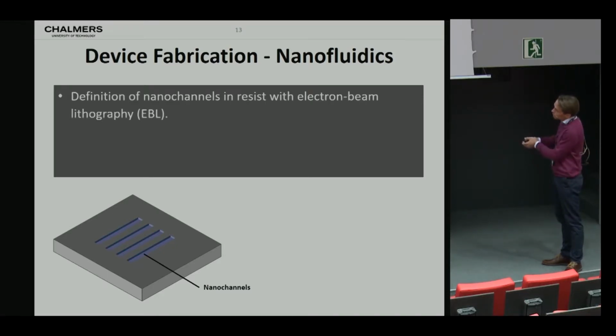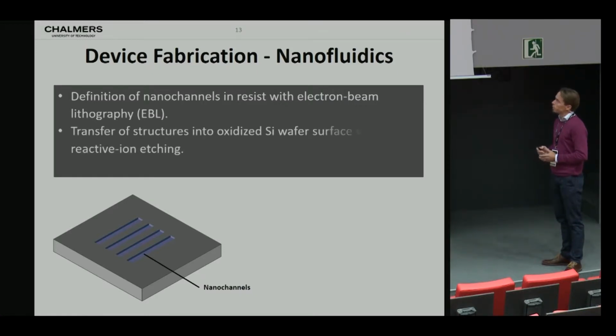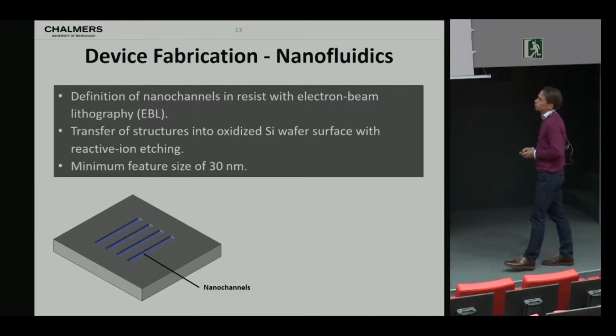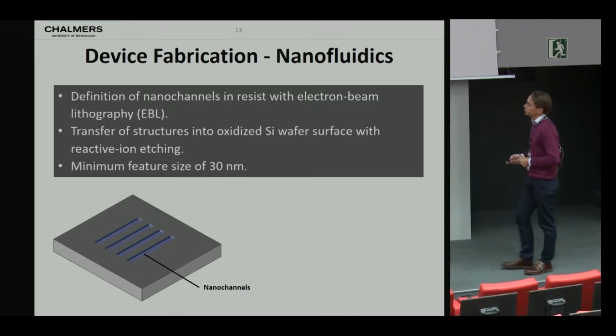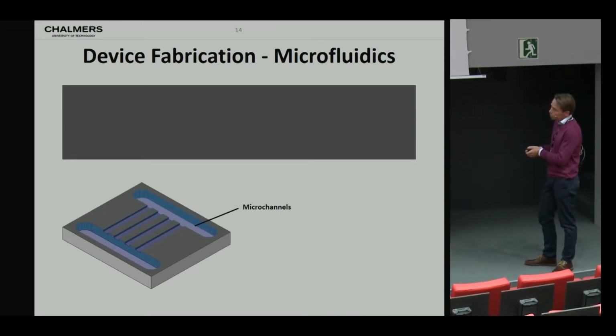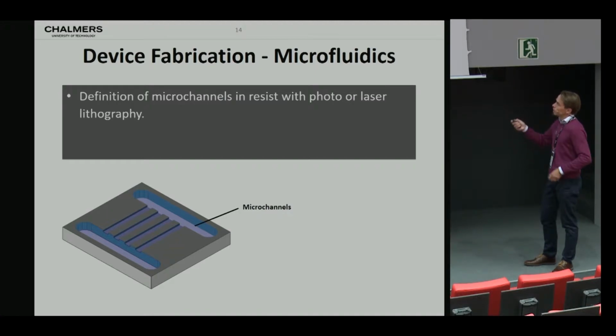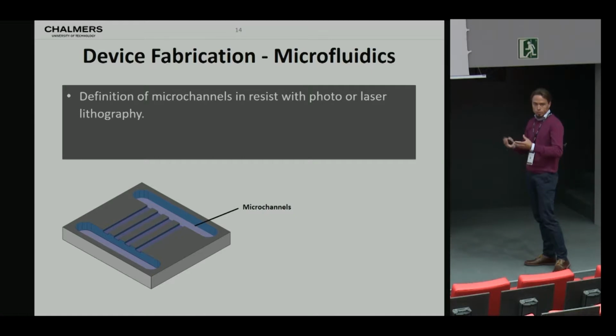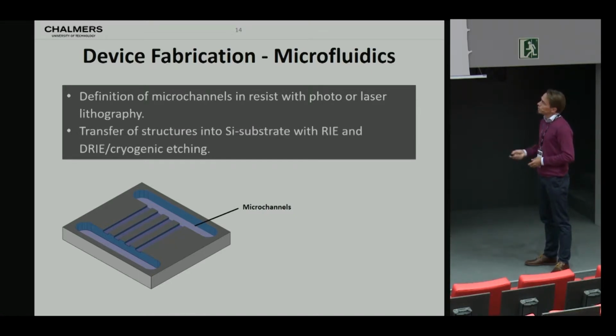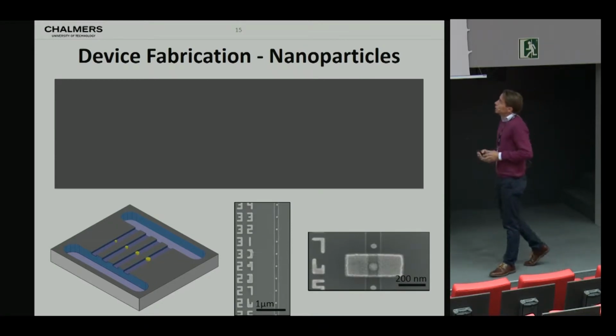Well, we start out with a silicon wafer, which is thermally oxidized to have a few hundred nanometer thick oxide layer on the surface. And then we define the nanochannels in a resist by means of electron beam lithography. We transfer the structures into the thermal oxide by means of reactive ion etching, which allows us to craft features with a feature size of around 30 nanometers. In the next step, we define the microfluidic system, which we need to connect this to the macroscopic world. And the strategy is pretty much the same, so we define them in a resist, this time using photo or laser lithography, because the structures are much larger. We don't need the resolution of electron beam lithography. And then again, we transfer the structures now down into the silicon by means of reactive ion etching or cryogenic etching.